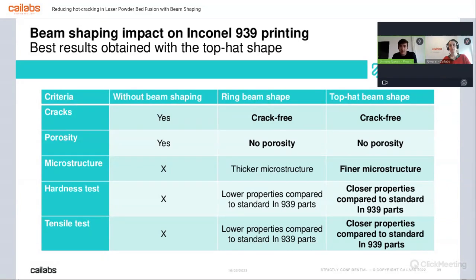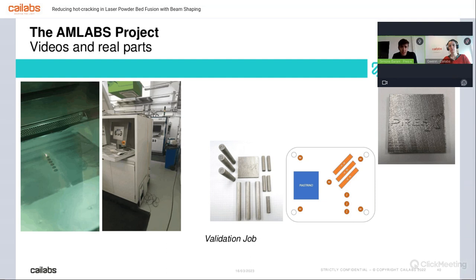We have a finer microstructure in the top hat, leading to the consideration that we have probably generated less structure that will introduce fragile effect. And the mechanical properties are closer to the ones that we obtain with newer machines, but without the cracks.